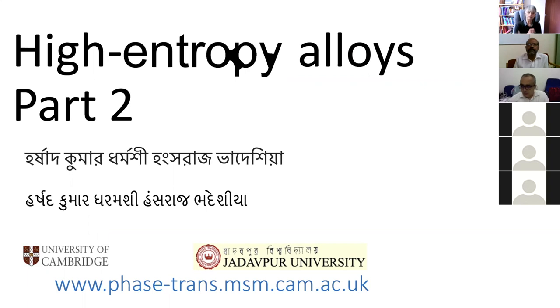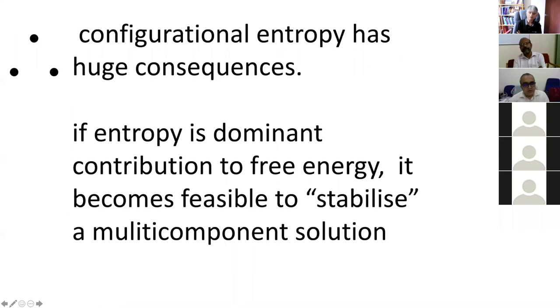I'll begin where I stopped at the last lecture, which is I introduced the term stability. I explained that configurational entropy has huge consequences by giving you examples of diffusion through the solid state, and also why the strength of materials collapses when the size increases, because the configurational entropy says there will be defects and there's nothing you can do about that. So if entropy is the dominant contribution to free energy, then it becomes feasible to stabilize a multi-component solution.